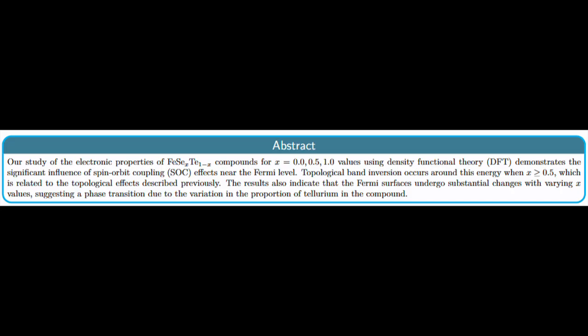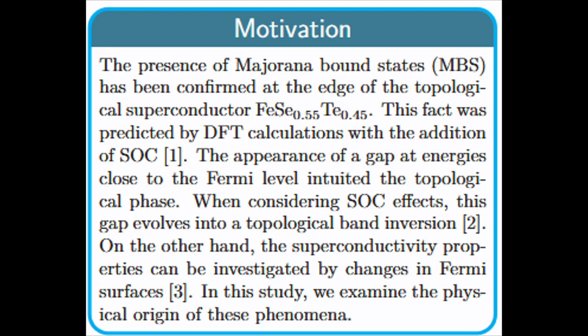The results also indicate that the Fermi surface undergoes substantial change with varying X values, suggesting a phase transition due to the variation in the proportion of tellurium in the compounds. The motivation for our research is to understand the influence of spin-orbit coupling on electronic properties, primarily at energies close to the Fermi level in iron chalcogenides.